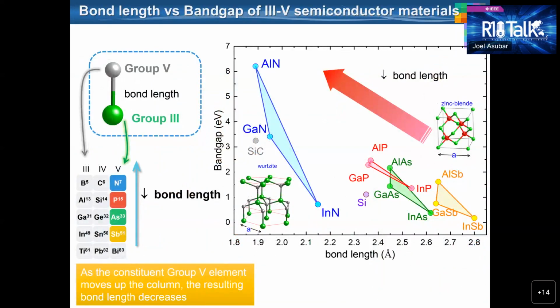Generally, for III-V compound semiconductors, as the constituent group 5 element moves up the column, antimony, arsenic, phosphorus, nitrogen, the corresponding bond length decreases. As can be seen here, the horizontal axis represents the bond length. Antimonides have the longest bond lengths, followed by arsenides, and then phosphides, and then nitrides.